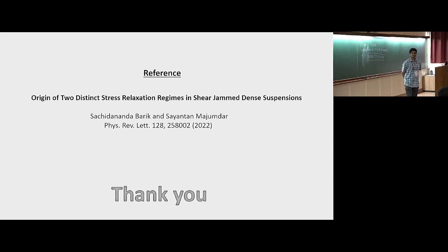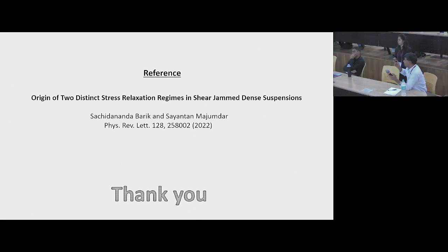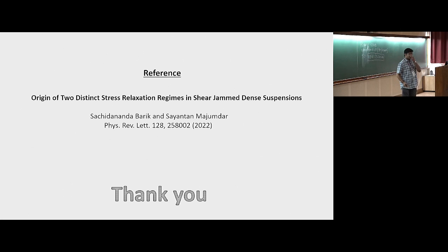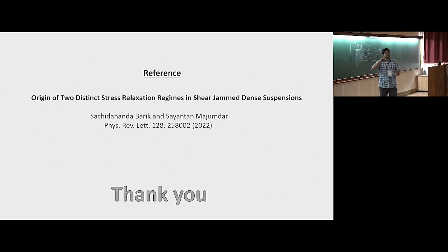Before this relaxation sets in, it seems to grow at a very short time. What is the origin of that? No, that is because we are applying shear at that time. That is a good observation. Actually, it is limited by the resolution of our instrument. We found that when you set some step magnitude, the instrument takes around 50 to 60 milliseconds to go to that step. During that time, that growth happens. But that is a transient regime.